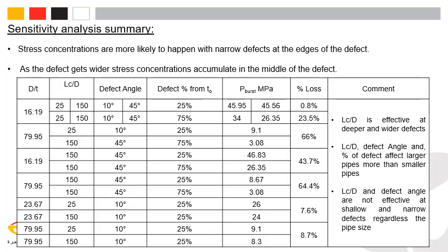Now I will give a quick summary about the sensitivity analysis. Stress concentrations are more likely to happen with narrow defects at the edges of the defect. As the defect gets wider, stress concentrations accumulate in the middle of the defect. So in order to judge the results that we came up with from the sensitivity analysis, I prepared this table